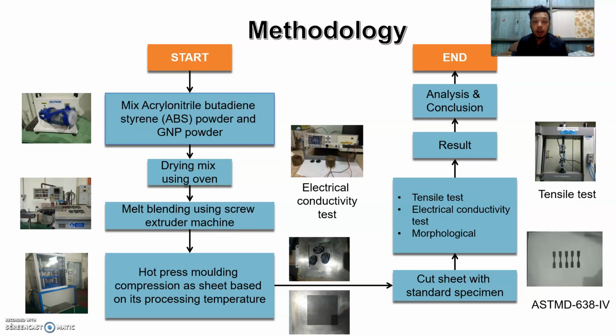Then we compress the composite using hot press molding to get the shape at a temperature of 190 Celsius, pressed for 1 minute 30 seconds with pressure 700 psi. After that, to get the sample, the shape will be cut to standard specimen ASTM type 4.